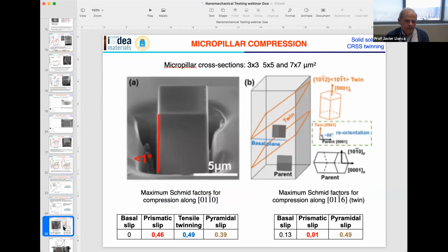Okay, this is what's going on in the case of basal slip. Let's go to a more complicated case, that is the case of twinning. Because twinning, as you know, is a rotation of the lattice, and in the case of magnesium you normally have tensile twinning. When you have tensile twinning, the parent grain oriented in this direction rotates by almost 90 degrees and takes a completely different orientation. So this is the 86 degrees orientation that is typical of twinning.